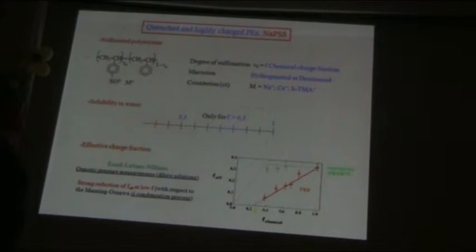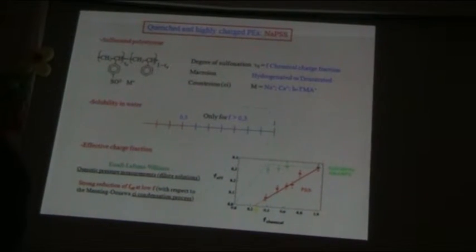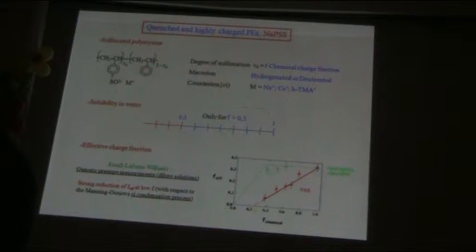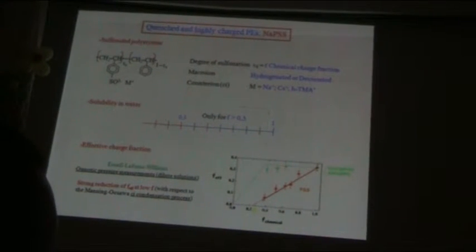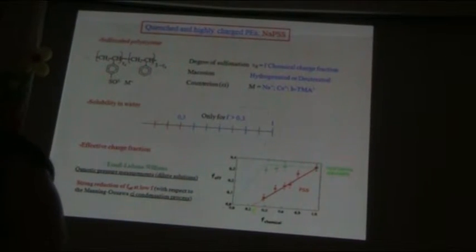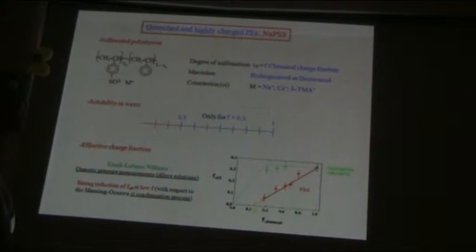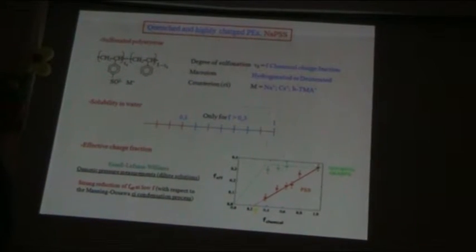In this case, of course, there is some fluctuation in the position of charges, and this fluctuation could have some importance. They are not important in the hydrophilic regime, but when you go towards the hydrophobic regime, when you reduce the electrical charges and increase the hydrophobic effect, the quenched and annealed polyelectrolyte behaviors are distinct. We will see, I hope.